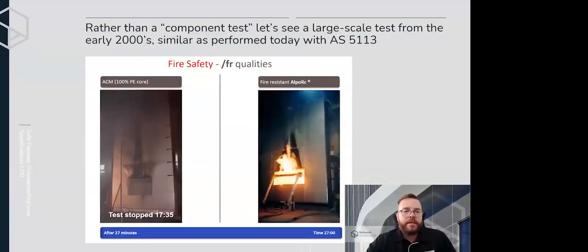And that's the test stopped. Now, one of the interesting things here is that it gave off a really big fire. However, you can see there that actually not all of the facade was actually alight. In fact, quite a lot of it still remains, which suggests how much heat that actually gives off. And the equivalent is about 5 litres of petrol per square metre for the polyethylene panels.